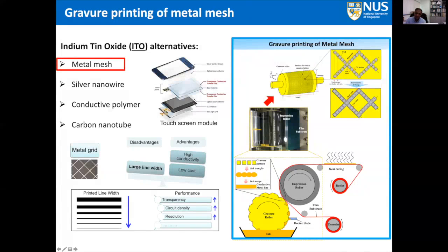So how do we go about doing it? The gravure printed roller mold is at the bottom here, and the ink is at the bottom, where the mold rotates through the ink, and then the ink is carried on and impressed onto this impression roller, where you see a very thin film substrate that passes through this impression roller, which is again cured on the other side and then rolled back again. So this entire process basically transforms the ink from the pockets, or the small holes, into some kind of an elliptical line being produced. When it is cured, they merge together to form a very thin line.